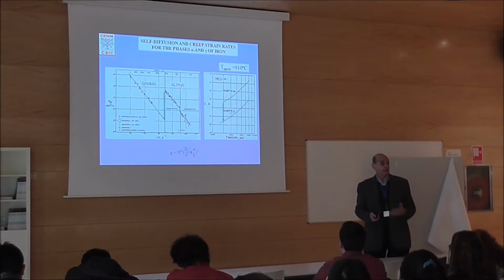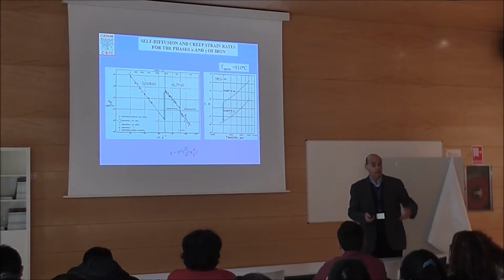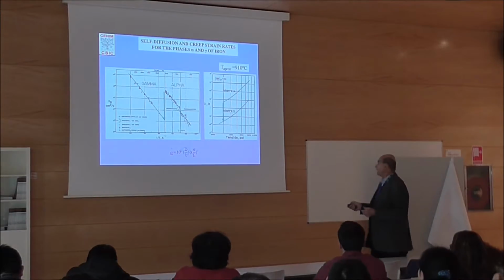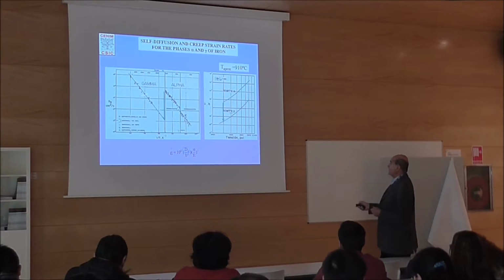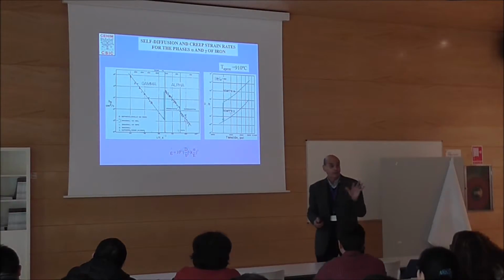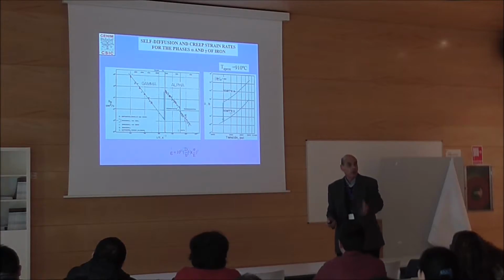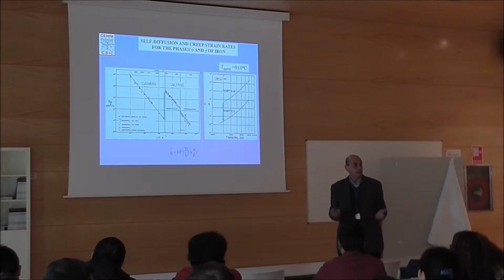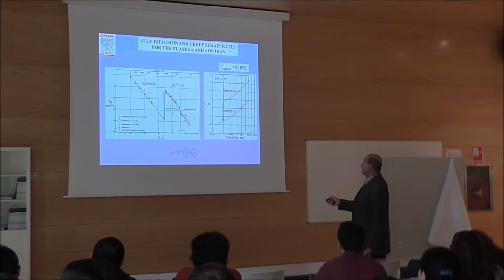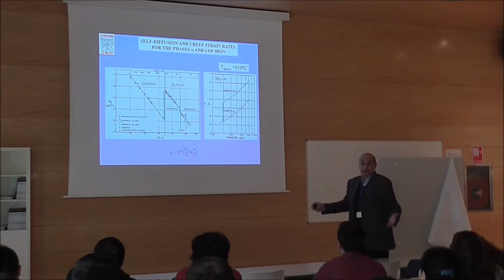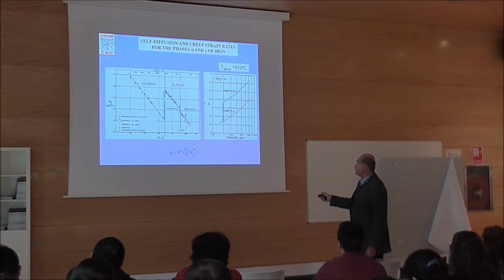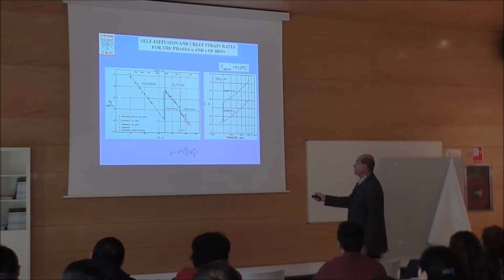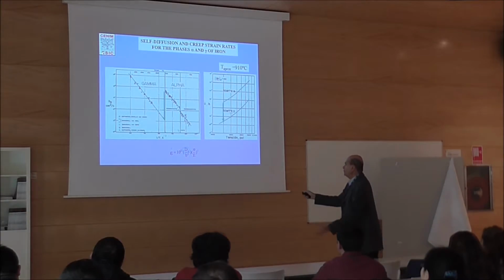The second thing I have to demonstrate, because I didn't want to go into the activation energies and all the things, and why do you like this? Well, I like this because of this. This is a diffusion experiment. This is not a creep experiment. This is just diffusion. This is the chemist who goes with radiotracer data and calculates diffusivity of chemicals. And if you go to alpha to gamma, this is iron. You see at 910, the alpha is BCC, an open structure. The diffusivity is high. And as soon as you change to a closed structure, it will diminish by 2 orders of magnitude, more or less. And this is a prediction from the chemist, from diffusivity. Nothing to do with creep.